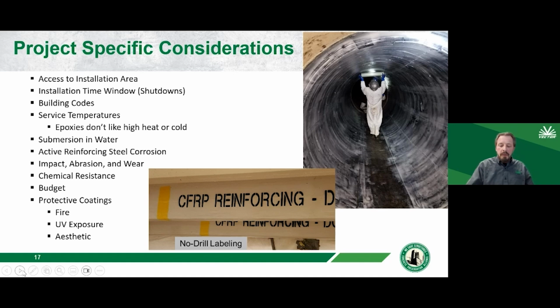Of course, building codes. So when we're using FRP in a residential or a commercial setting or a facility that is habitable, these are things that we're going to have to look into and make sure that if there's fireproofing that needs to be installed, that we account for that in the development of the project. And then of course service temperatures. So epoxies don't like high temperatures. Once you get up to 140 degrees Fahrenheit, 150, the epoxies have a tendency to relax, and that's not good for the FRP product.